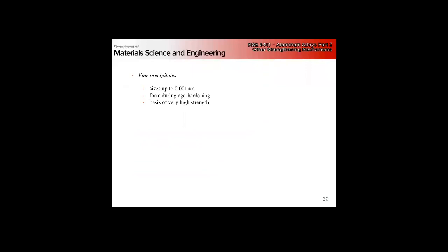Getting rid of recrystallization, is that mainly a problem we're going to see only in aluminum, or if you're looking at a steel system would you also have to? No, in steel there are certain steels where grain boundary pinning is very important, where we want to retard grain growth. It's just that in aluminum it's a primary mechanism.